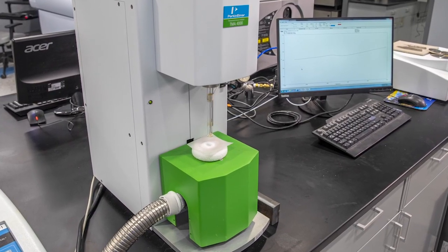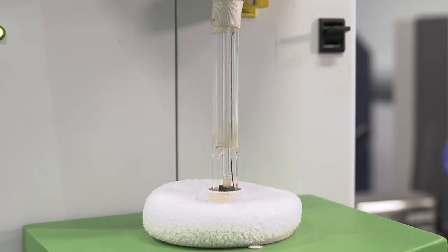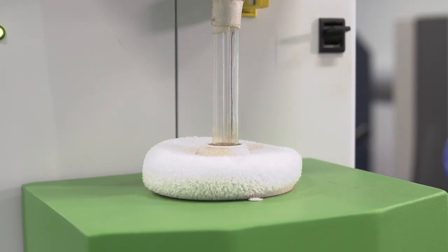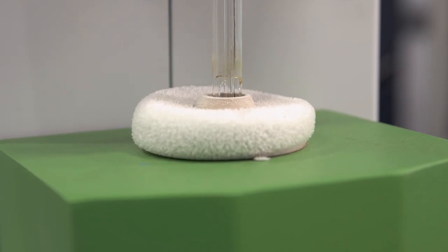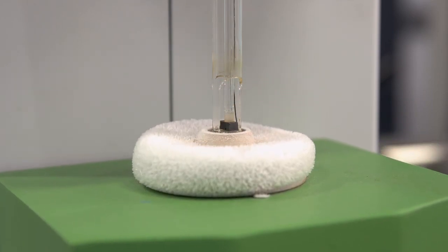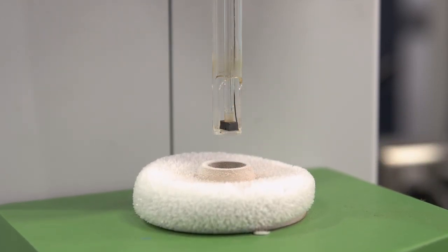At EPIC, we have a TMA. And a TMA is where you put a glass probe on top of that polymer sample and you cycle it from the lowest temperature you want to the highest temperature you want. And getting back to that molecular structure to property relationship, we can adjust that molecular structure to give us a coefficient of thermal expansion that's appropriate for the customer's operating temperature range, in addition to making sure that Tg is outside of their operating temperature.